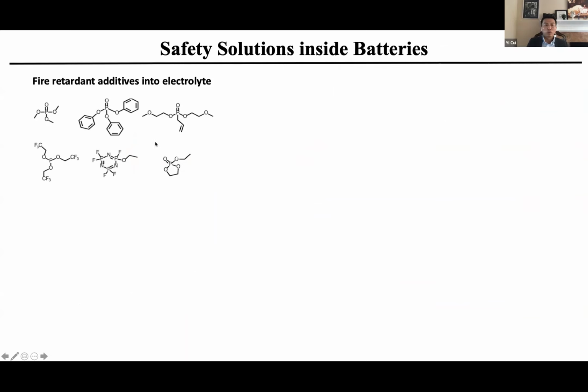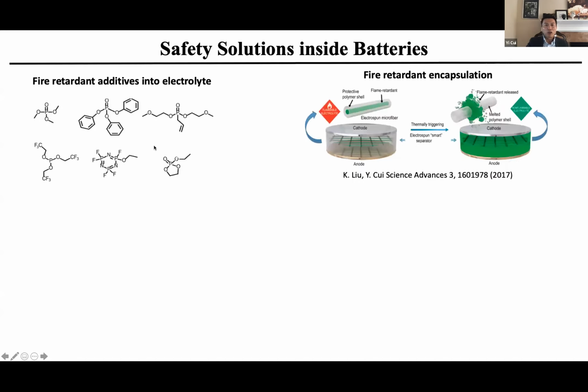First, the idea I want to point out is already in use. People use fire retardant, adding an additive into the organic electrolyte. And we also recently invented an idea: we need to encapsulate this fire retardant into a polymer. The reason is the more fire retardant you add in, the more you increase the viscosity of the electrolyte. So the lithium-ion conductivity in the electrolyte becomes smaller, harder for the battery to operate. So instead, we encapsulate this green-colored additive, this fire retardant, into a polymer. Until you heat to a certain temperature, the polymer melts and releases the fire retardant, knowing the danger is coming, and then quenches the fire.